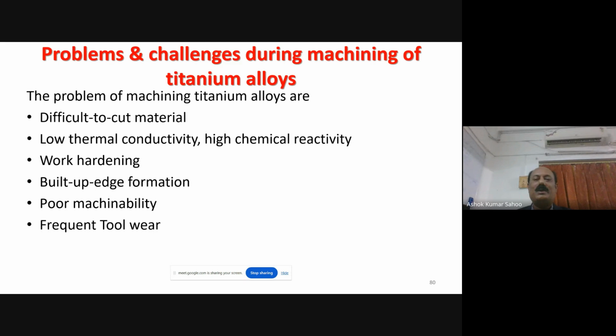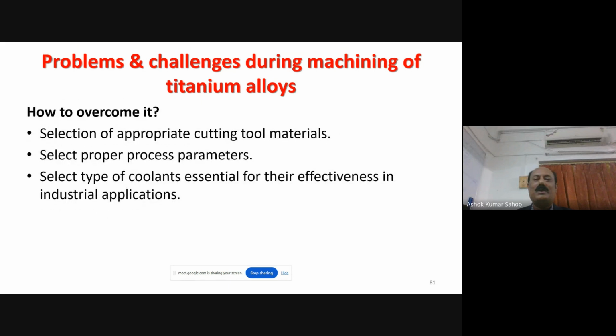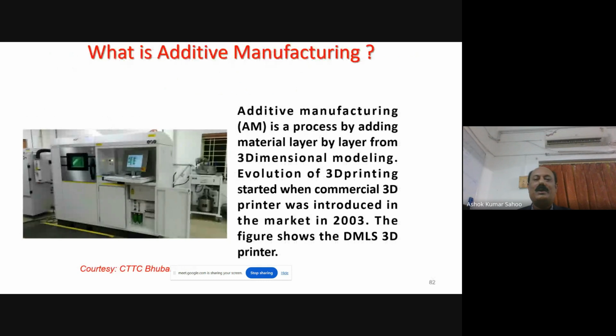And whenever you machine the titanium alloys, it induces built-up edge formation due to adhesion of the chip particle at the chip-tool interface, which induces poor surface quality and dimensional accuracy, and thus in general the tool wear is higher, and finally the machinability is poor. So these are some challenges in machining of titanium alloy. To overcome it, the appropriate selection of the cutting tool material, cutting tool geometry, machining parameters, and coolants is especially essential for the effectiveness of industrial applications.